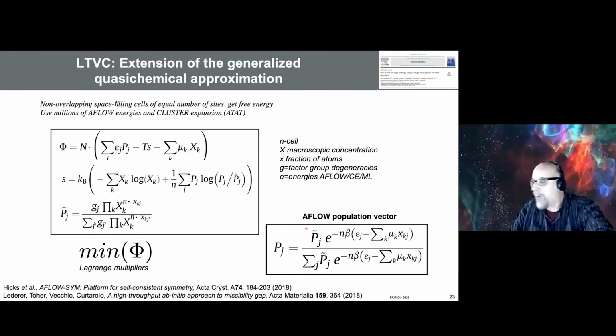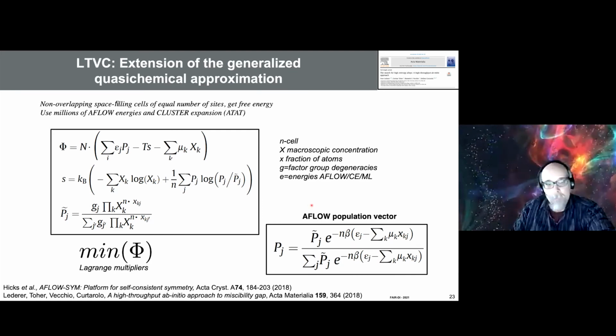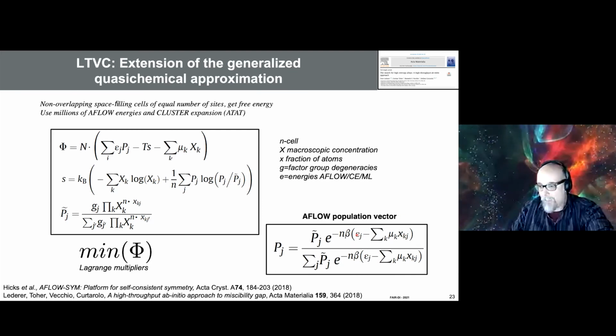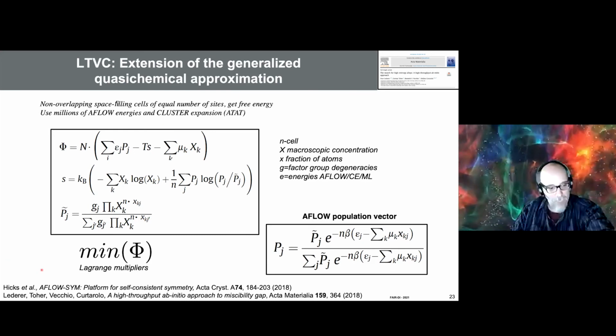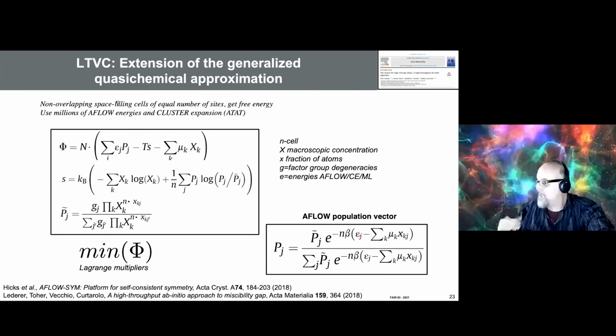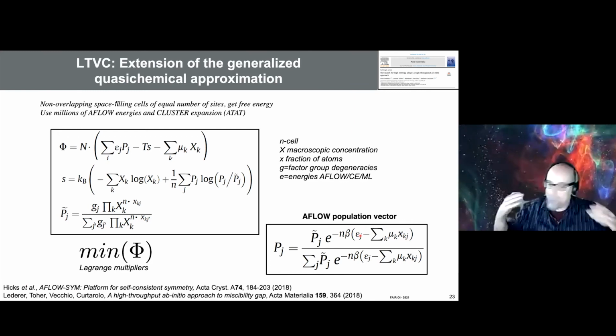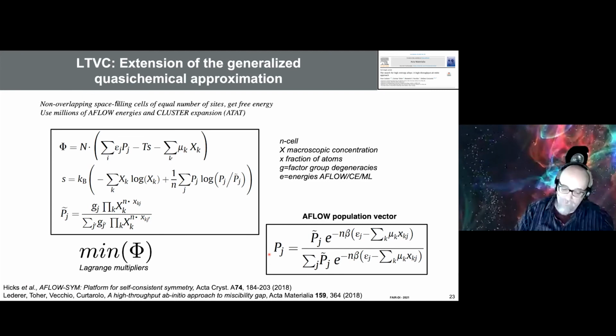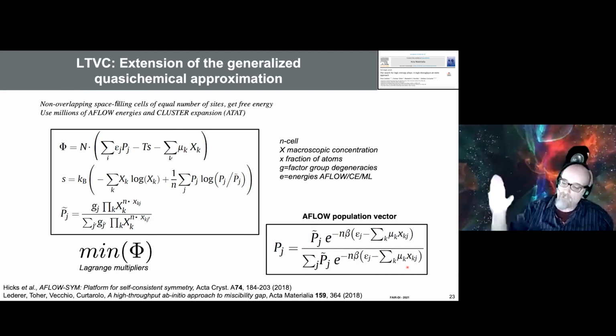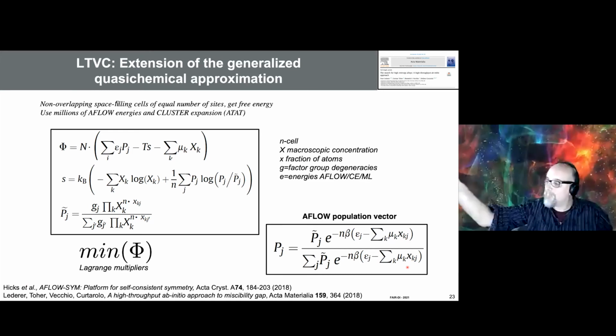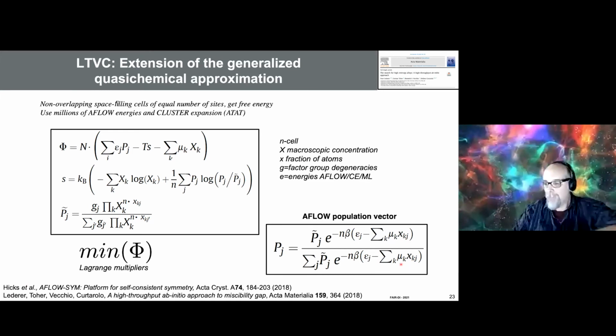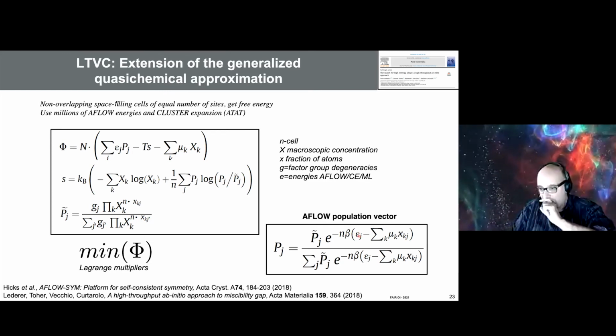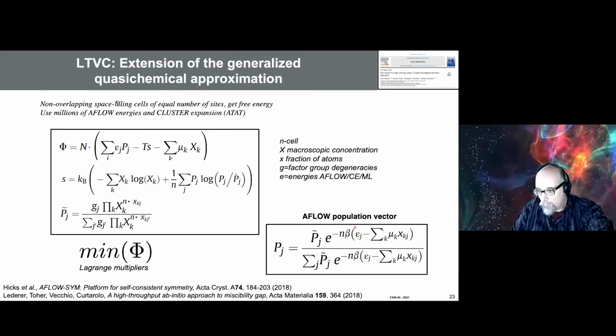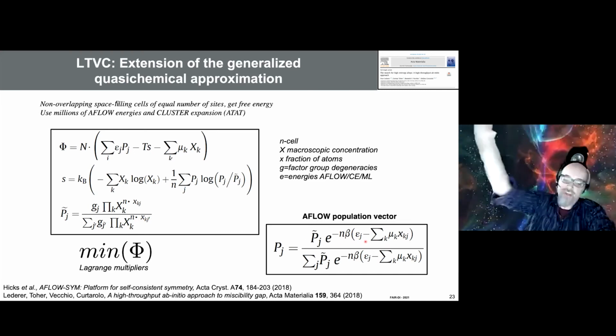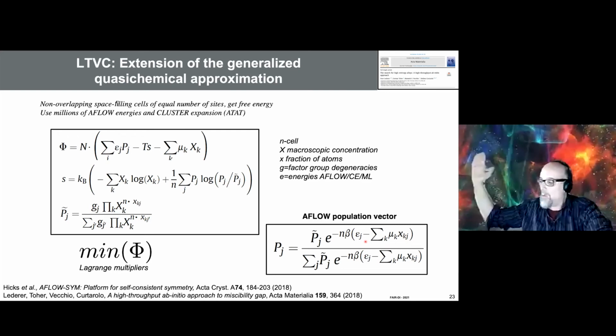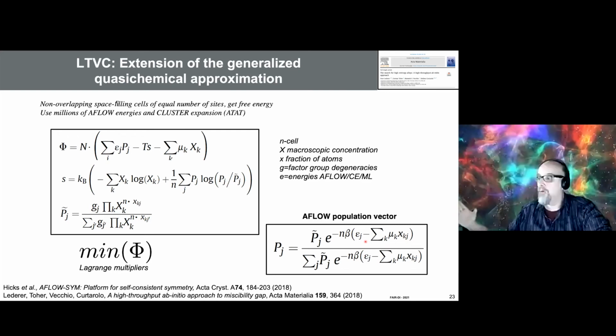So you see the power of POCC and these energies. By the way, if you want to clusterize them, as we did in this article, you have more of them. And if you want to add machine learning, the more the better. You're going to have a gigantic population vector, and you just do all the normalization, and you see how this vector changes with respect to temperature. And this will give you your order-disorder. So machine learning, cluster expansion, AFLOW, NOMA, everything goes here on this epsilon. You do all this operation, and then you're going to have this gigantic vector, and you see how it moves in the space of probabilities, and find your phase transitions.